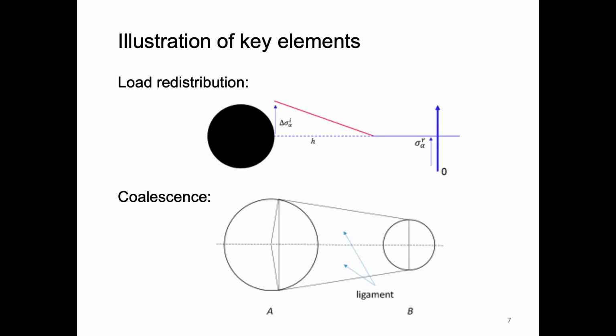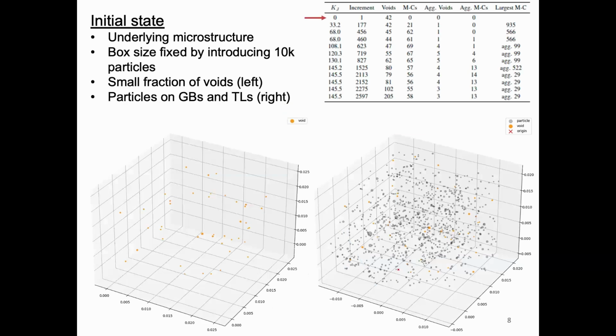If you have a void that forms, then the excess of stress that happens at the void end is redistributed linearly to a certain distance that depends on the void size. This is the horizon. And if there is a particle within the horizon, then that particle sees the increasing load. And if there is another defect already formed in the horizon, then there can be a coalescence if the condition for coalescence is met.